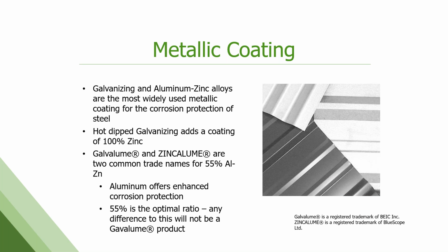So the metallic coating portion on the steel is really important. And the two most common, of course, are hot dip galvanized and Galvalume or zinc aluminum. Hot dip galvanized is 100% zinc coating, been around a very, very long time. Most people are familiar with it. Galvalume or zinc aluminum are trade names for a 55% aluminum, 45% zinc combination, which the aluminum offers enhanced corrosion protection. And that 55% ratio is the optimum ratio to get superior performance out in the field.